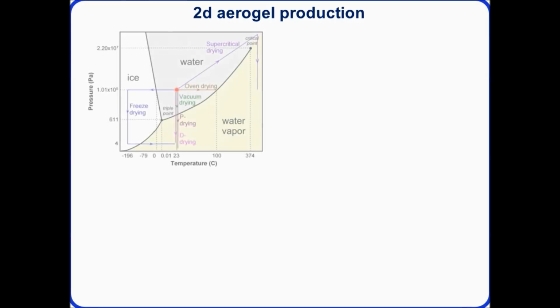Okay. So the other approach is to take the ink again directly from the microfluidic processor and freeze it in a refrigerator, and we can then apply a vacuum, which causes, if we look at this phase diagram, we can perform this freeze drying process. So we freeze the water to ice, we apply a vacuum, so we are reducing the pressure, and then we let it heat up, and the ice turns into vapor, which leaves behind a porous graphene structure.